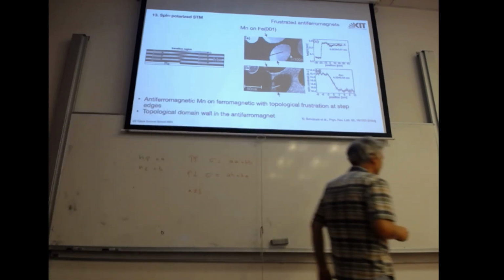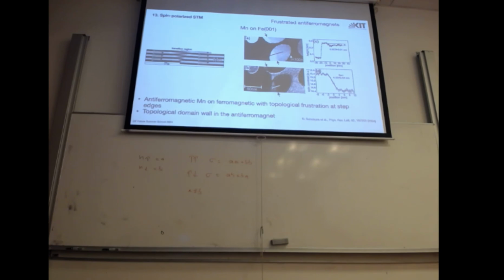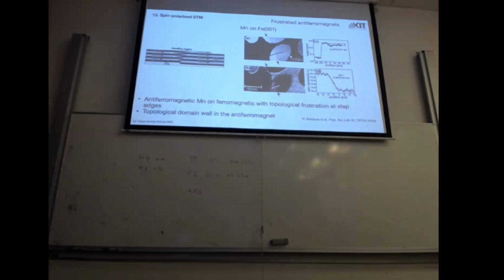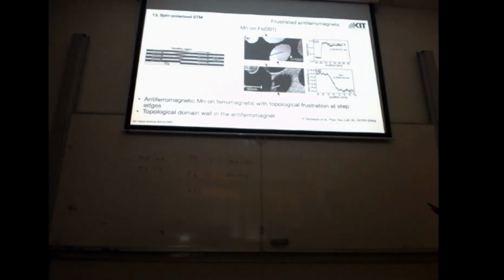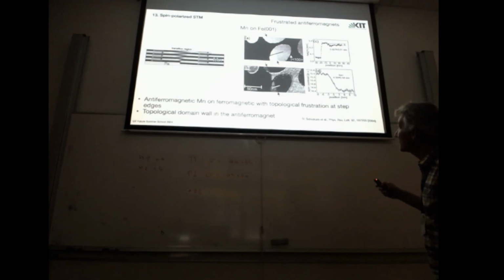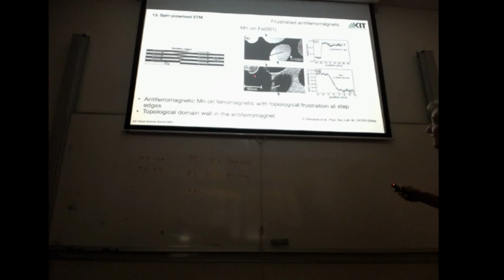Okay. I don't know if you can see that. So these are atomic steps of the manganese. This is N and N minus 1 layers, going from bright to dark. So these are the antiferromagnetic layers. But there's this kind of weak contrast, which is this buried step. And we expect a domain wall here, and indeed, this is roughly the same height, but you also go from even to odd numbers of layers, and you see this frustration here in the antiferromagnet. So we can image domain walls in an antiferromagnet.